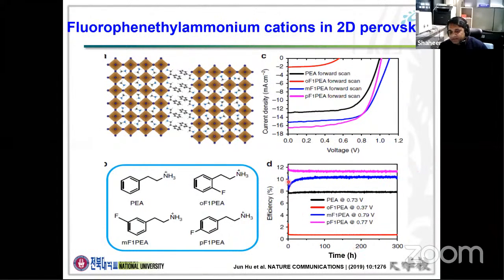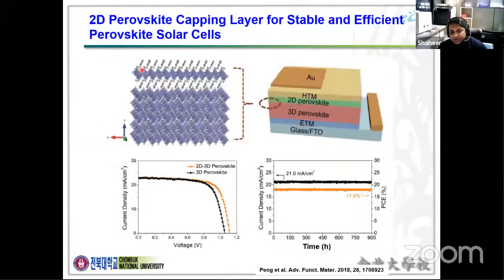You can see in this case the device performance is almost stable for 300 hours, which means almost zero degradation after 300 hours. Similarly, in the other case, you make the layer by layer structure: a 2D layer, 3D layer, and then a 2D layer. This kind of layered structure is a kind of quasi-2D perovskite solar cell. They also found the stability of the cells improved up to the 1000th hour, which is remarkable in the area of perovskite solar cells.